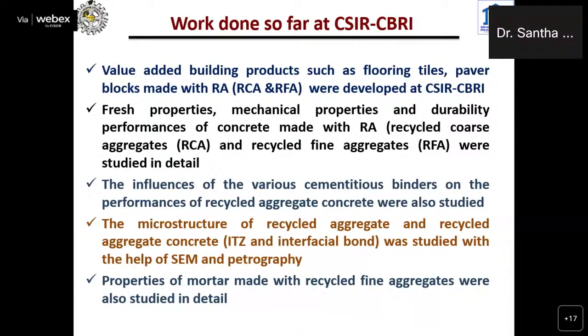And we have used various cementitious binders for making the recycled aggregate concrete. The microstructure of recycled aggregate and recycled aggregate concrete, particularly the ITZ and interfacial bond, under the effect of the cementitious binders and the new cement paste, we have studied with the help of SEM and petrography. The properties of the mortar, which is required as the joint material as well as the matrix used for the concrete, we have analyzed separately and studied in detail. Then go to the next slide.